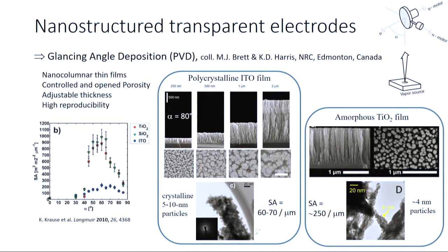So in our group, we're working with nanostructured transparent electrodes, which are prepared by a simple physical vapor deposition method. This is made by our collaborators, Michael Brett and Kenneth Harris in Canada. And the principle of this deposition process is that the vapor flux arrives at a very high angle regarding the substrate, which is furthermore rotating, and this allows for deposition of porous films. And in this specific case, we work with nanocolumnar thin films, and the nanocolumns grow perpendicularly to the transparent conductive substrate.